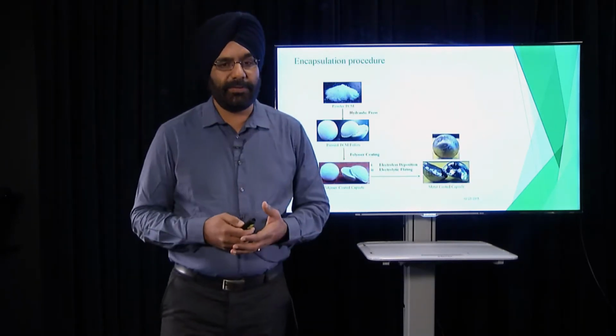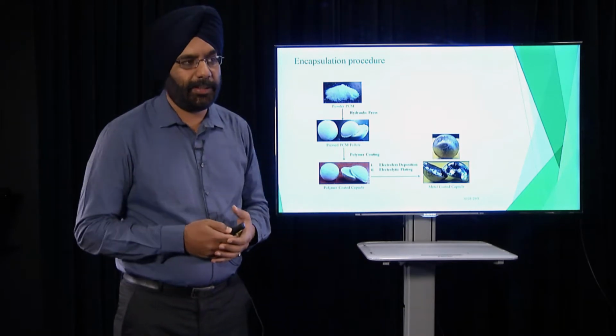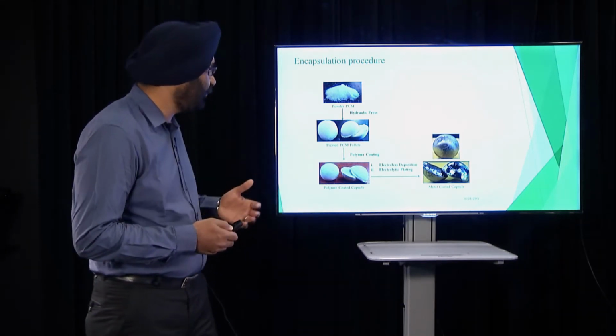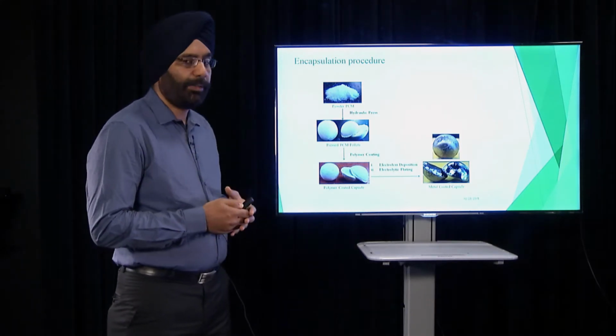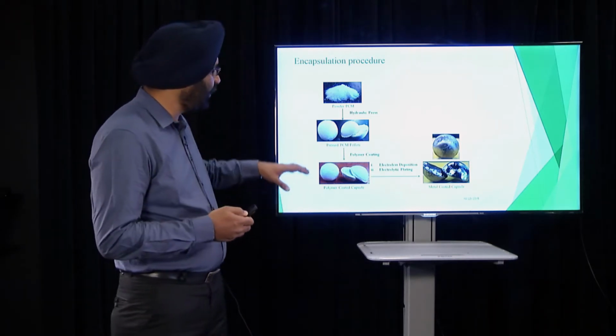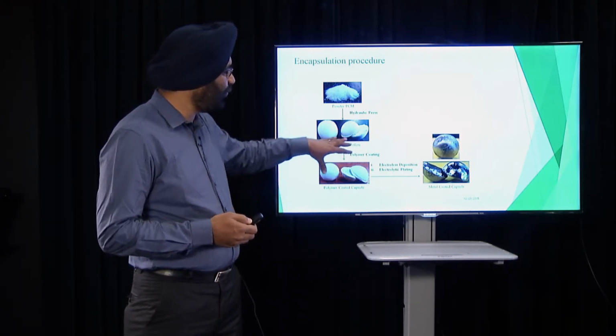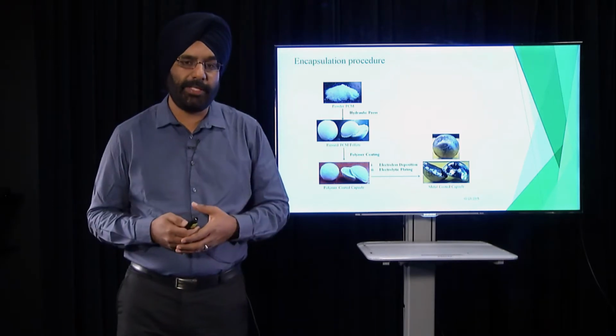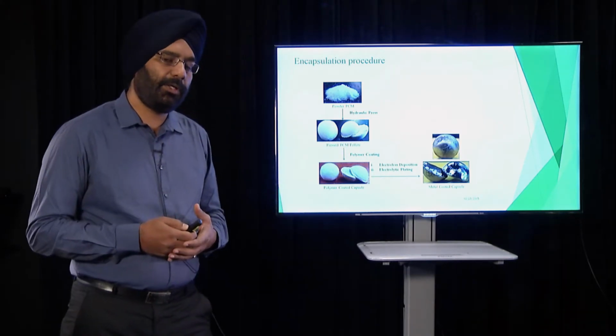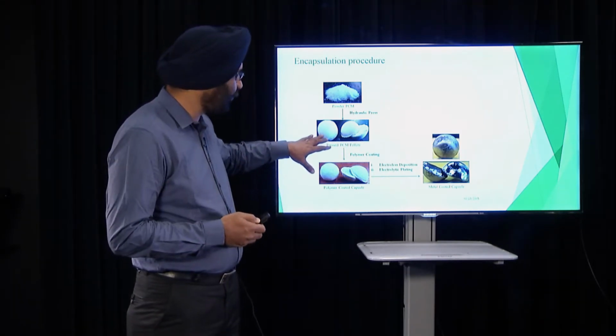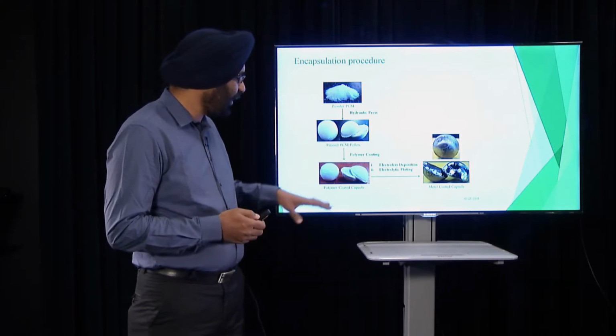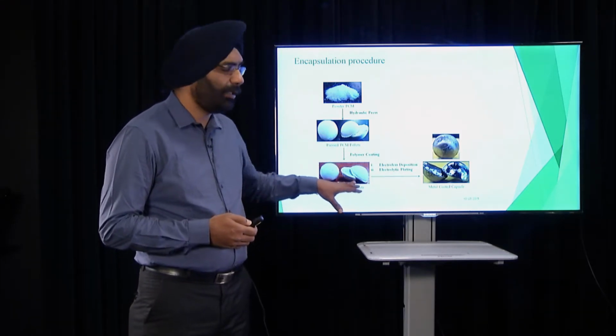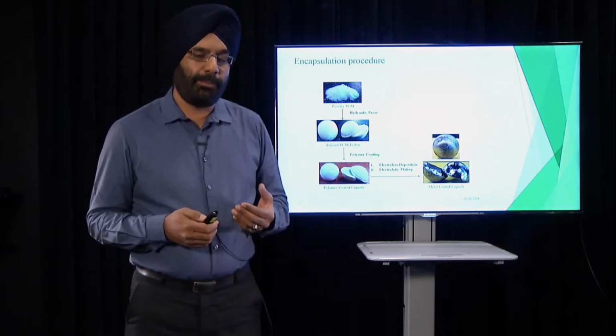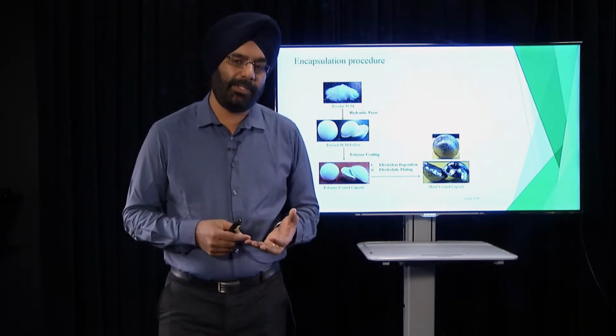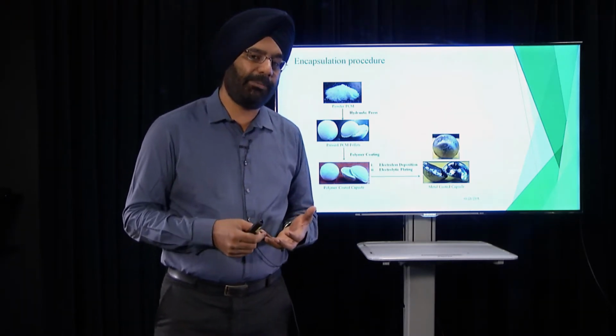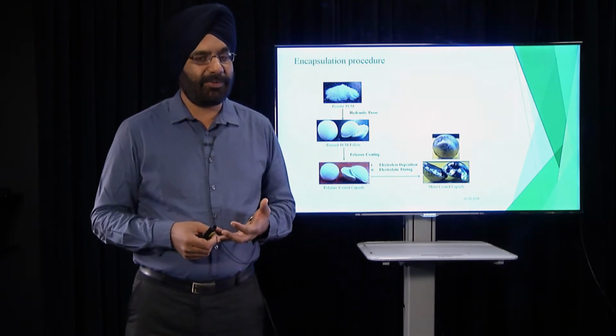So, this is the process which we developed, and it's highly successful. We started from the powder PCM, which is the phase change material. We converted that into solid hemispherical or spherical balls. So, this is spherical and this is hemispherical, and then we coated it with a polymer. Now, the polymer is flexible, the polymer is selectively permeable, but it does not have the strength.